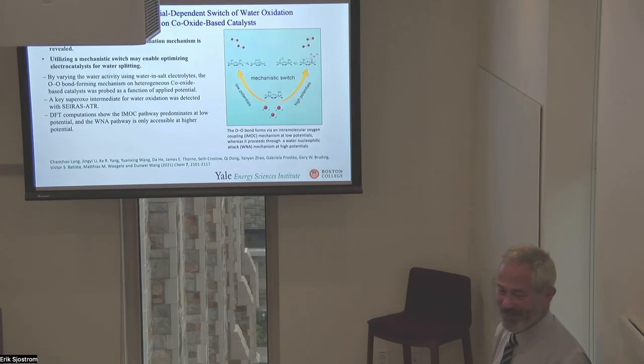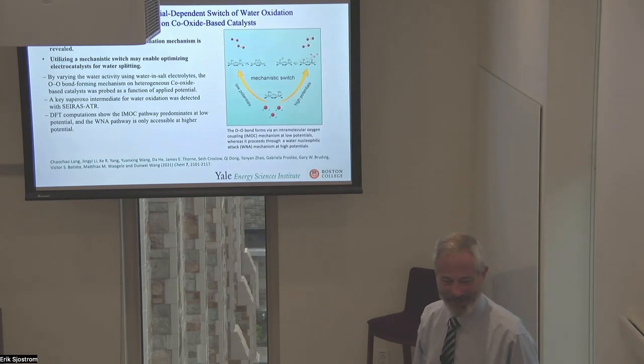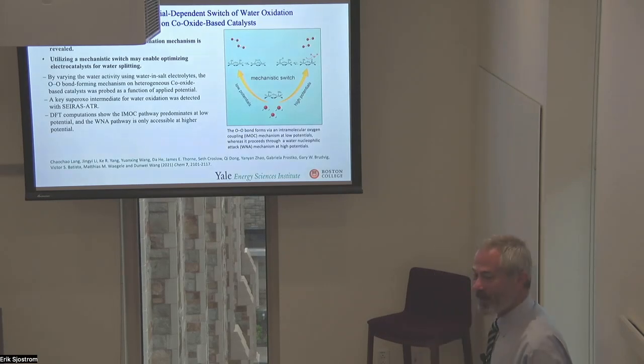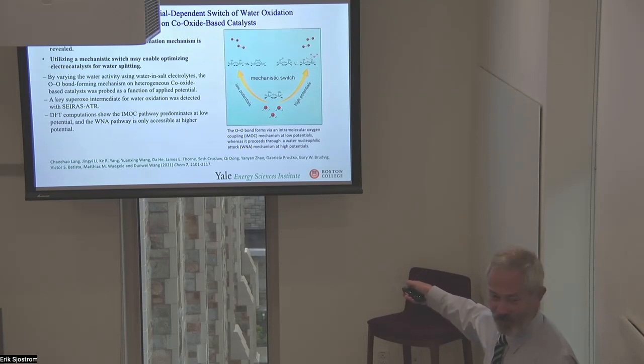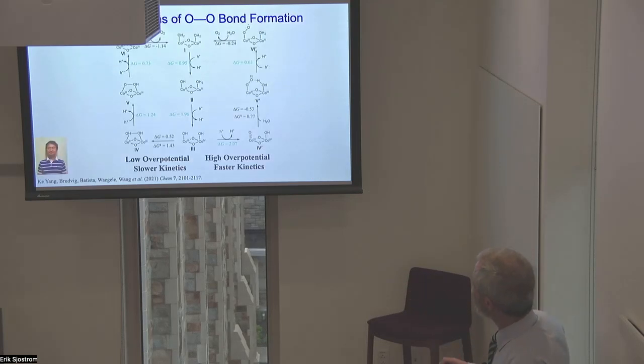One of the things that Dunwei found, which is really interesting, is that there may be different mechanisms depending on the potential of the system. This is some work that was done with the cobalt oxide catalyst. What was found is that at low potential we have one mechanism, and at high potential a different mechanism, which was determined by varying the water activity and seeing different isotope effects in low and high salt concentrations. And this was modeled by Yang.